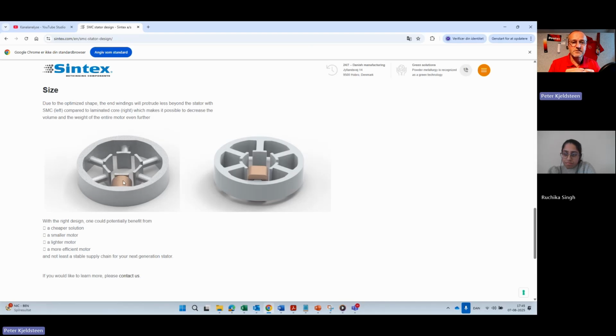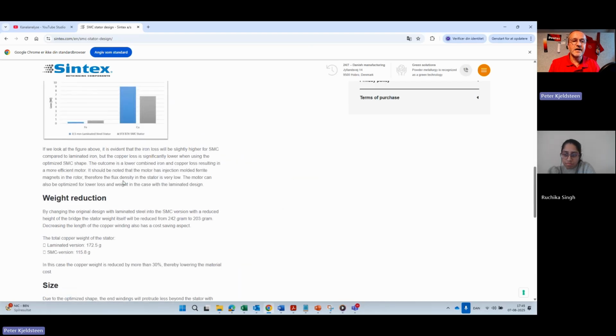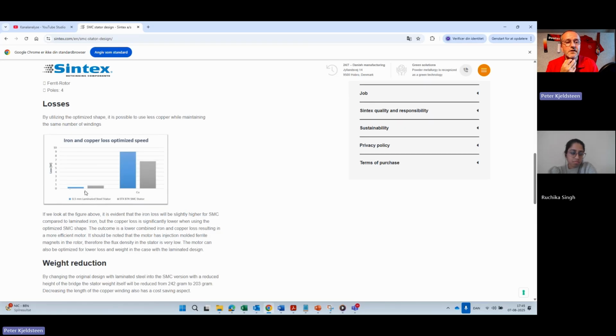And when we talk about losses in a motor, we have an example here where we made calculations of losses. You can see that going from a laminate to the SMC, the iron losses more than double. But due to the lower amount of copper, the copper losses are reduced linearly with the amount of copper you save. And if you sum these up, the total loss in the stator is far below by taking this design. So SMC is not necessarily a smart material, but it's a material that enables smart design. That's how I would put it.